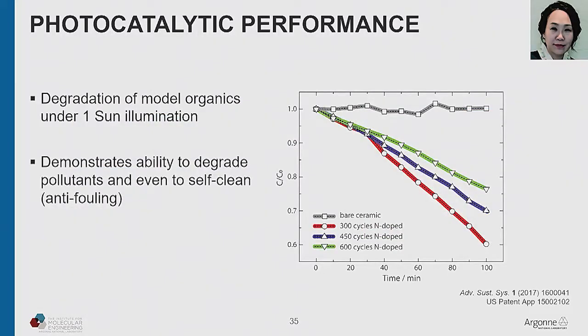And it works. If you take one of these membranes and you provide it with organic molecules as model foulants and expose it to sunlight, simulated sunlight in this case, just normal titanium dioxide, you see no degradation of any kind because there's just not enough UV light in a solar spectrum to have any measurable activity on this time scale. But you can see the ones with the doped titanium dioxide are quite effective at degrading those organic foulants.